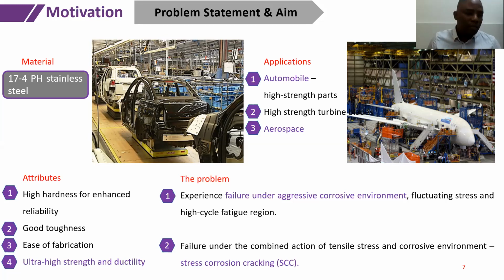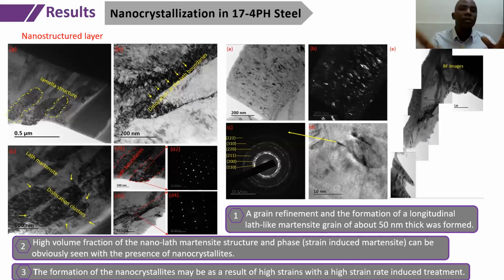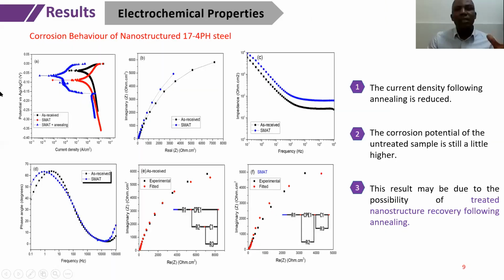Now the TEM process says that there's a structural, a longitudinal, about 50 nanometer grain on the surface of the material, and we have some dislocation clusters on the surface of the material, and this actually contributes to the improved properties of this material. And in terms of corrosion properties, combining SMAT and annealing treatment, you notice that our sample experienced a very low corrosion current density. And from literature, the lower the current density, the better the corrosion properties. And this actually shows that we have an improved property.